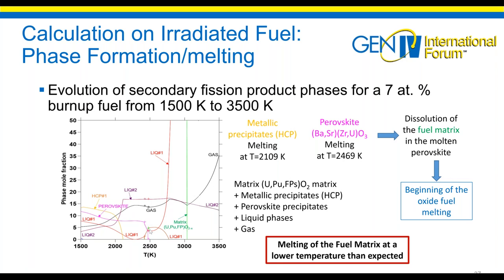But what is important to look at is that you will have a liquid forming. Therefore, you will have the dissolution of the fuel matrix in the molten perovskite. So locally, because this type of compound is just local in the fuel, you will have the beginning of the oxide fuel melting, and the melting of the fuel matrix is really at a lower temperature than expected locally.